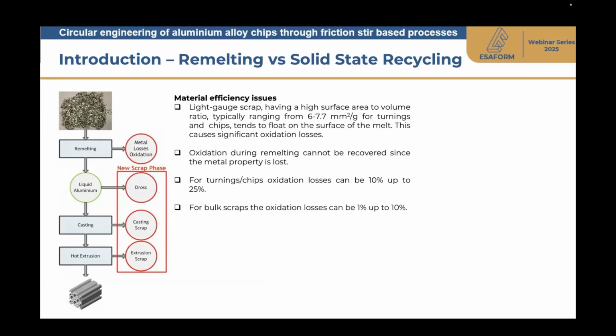It should be observed that in terms of material efficiency, traditional remelting recycling processes are characterized by strong metal losses due to oxidation, which are definitely critical, and even more critical as actual chips are considered. Namely, if we consider bulk scraps, the oxidation losses can be between 1% and 10%. But in turn, if we consider a strong surface to volume ratio in the parts to be recycled, so chips, the oxidation losses can be from 10% to 25%. This strongly reduces the material efficiency or the whole efficiency of the remelting process.